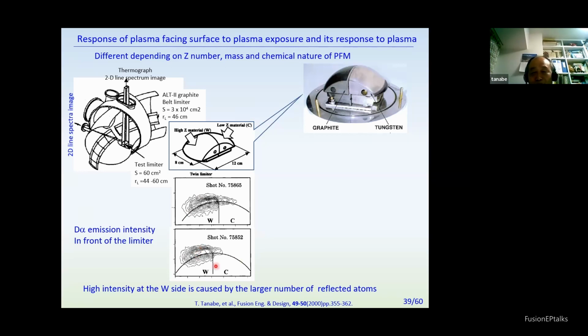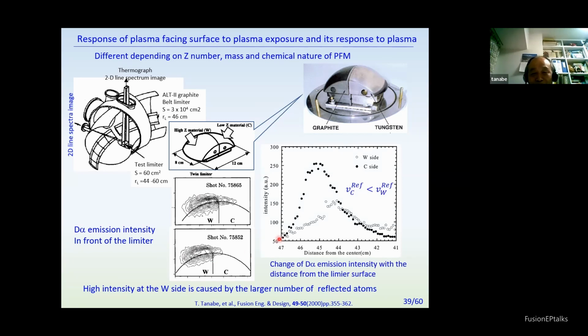Also, moving from the surface toward the plasma, the emission decays. In the case of tungsten, it penetrates deeper because the reflected velocity of the reflected particles becomes larger for heavier materials compared to carbon. So there are clear differences in hydrogen recycling due to mass differences and also the numbers involved.